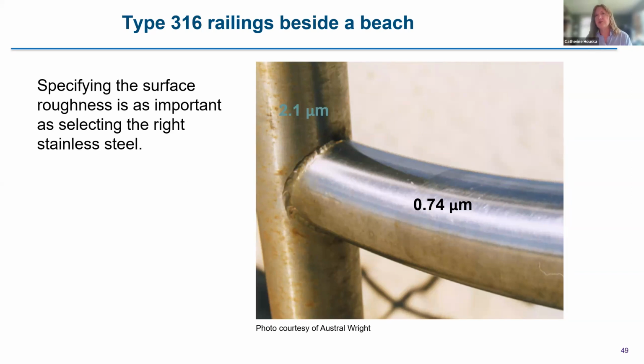This is an example from Australia. The specification called out a rough finish. The supplier tried to talk them into a smoother finish, asked if they could polish an area, and this corrosion difference is strictly related to the surface roughness. If the whole railing had a finer polish, then it would have not had a corrosion issue.